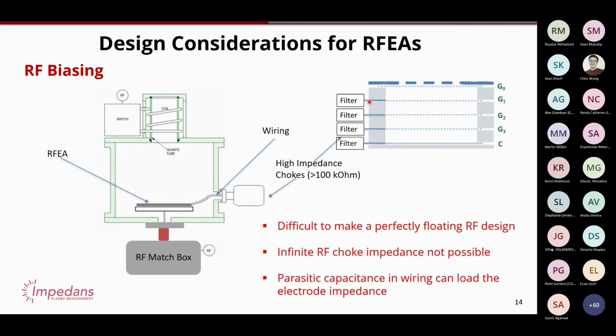But what you need to put in place are these high impedance chokes. More than 100 kilo ohms, or a few hundred kilo ohms, is usually enough to make sure that you don't load the chuck too much, that your data is still representative, and that you protect all the measurement circuitry from RF. So usually these chokes are placed in a feed through, the vacuum interface, so no RF exits out to the measurement electronics. But once these are in place, it means that you can actually take these ion energy measurements when an RF bias is being applied to an electrode.